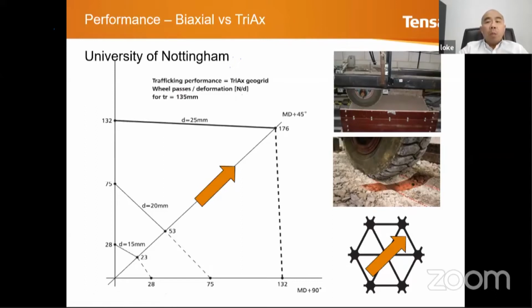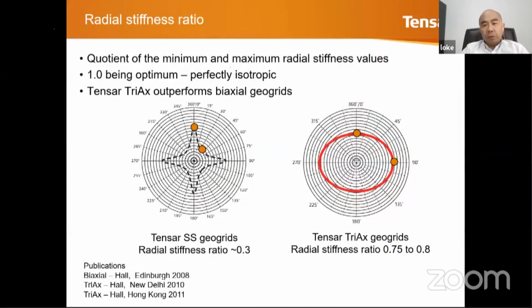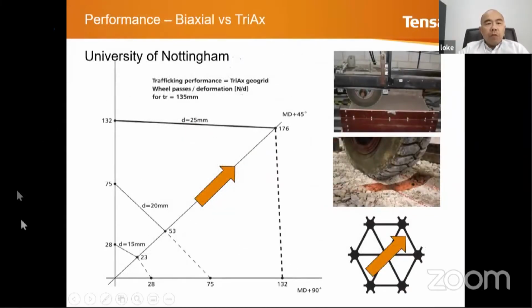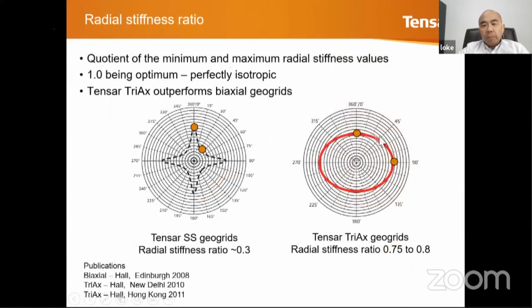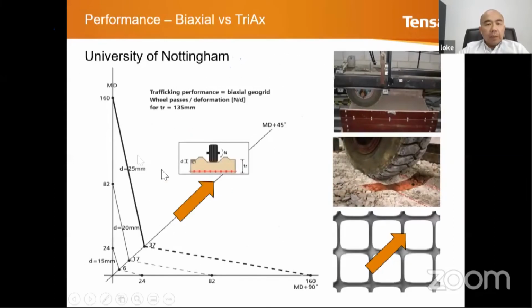And that explains why a triax or hexagonal geogrid performs better than a biaxial or square geogrid, because the wheel loading exerts radial stress, and radial stress has to be taken by a radial form of geogrid. If I take this quadrant and make it into 4 quadrants, I get this shape, which is the same as this. And this is one quadrant for square geogrids, and putting it in 4 quadrants, I get this.